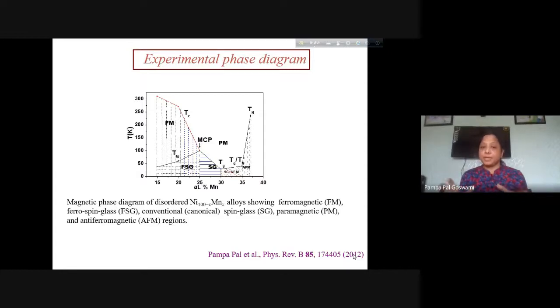So this is the phase diagram. Already I have done it on the NiMn system. The phase diagram shows, on changing the concentration of manganese from 15 to 37%, we can see the phase change of magnetization. For the concentration of 15% Mn, we found two different magnetic phases, like ferromagnetic and ferro spin glass. So we can see that the magnetic phase diagram of the disordered alloy system shows different magnetic phases like ferromagnetic, ferro spin glass, conventional spin glass, paramagnetic, and antiferromagnetic regions.